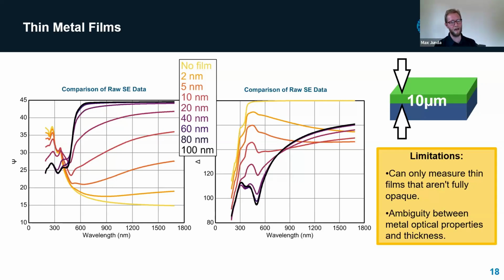But what happens is you kind of reach an asymptotic behavior here, whereas we get to even thicker, 60, 80, 100, these dark lines, they all start to become about the same. And that's basically the case where these films are getting thick enough that they are transitioning from partly transmitting to being fully opaque. And so that's the point where we lose the ability to measure the thickness of films. So it can only work where the metal is not fully absorbing.